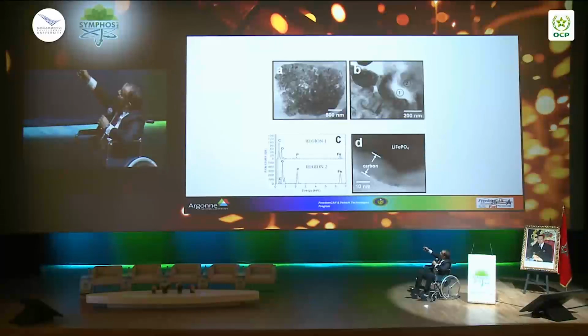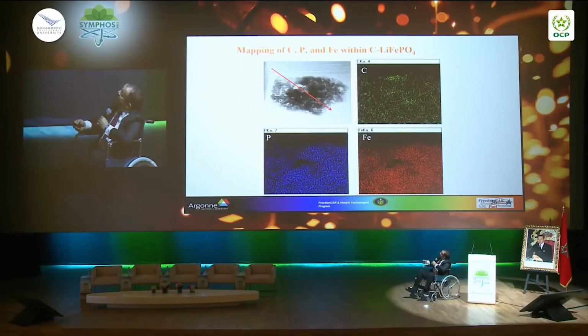And of course you can do the coating, as I mentioned. You can do coating at the surface and within the pores. The best way to do that is cracking propylene or toluene gas, because gas goes everywhere before you basically decompose it. As you can see, we have carbon at the surface of the particle and carbon inside the pores for better conductivity. And this is an EDS map that shows the carbon is everywhere, not only at the surface of the particle, but inside the pores as well.